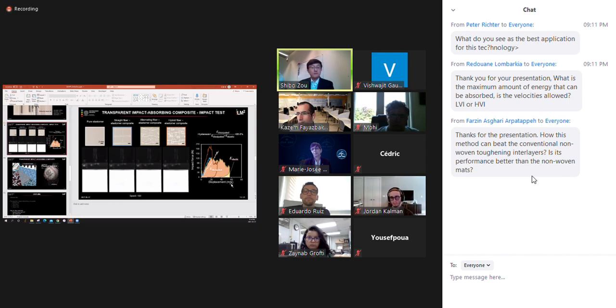For the specific specimen that I made, I tested also under static loading. The maximum is around 5 or 6 joule, and then I tested at 5 joule impact energy under the falling dart impact tester. I think this is pretty much the limit of the current design. But by changing the design, it can be improved. Even though I'm using a film, under impact there are only those fibers, like 3 fibers along each direction, along the way of the falling dart, that actually function to resist the penetration of the dart. If we are able to increase the fiber density, and depending on the size of the falling dart, we can of course increase the total energy absorption of this composite.